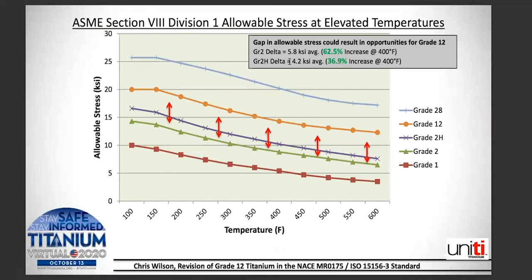Versus grade 2H, it's not quite as high, it's 4.2 KSI average, but that's still 36.9% increase at 400 degrees Fahrenheit. So the implication there being, by going to a stronger material, higher tensile strength material, you will be able to reduce the wall thickness in a pressure vessel application, thus saving you money on material costs.